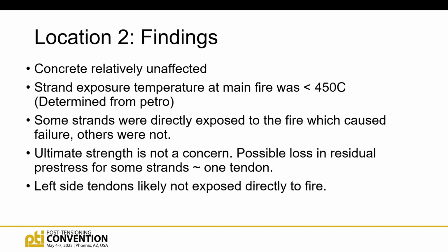So our conclusions, and it worked out pretty well for the DOT, the concrete was relatively unaffected. We weren't concerned about that pre-stressed top slab, which was the main thing that caused them to reject that other span. The strand temperature during the fire, at the main fire, the biggest fire, was less than 450 Celsius, determined from our petrographers, so that's good news. That tells us that the other strands, which are at lower temperatures, were likely less affected or almost unaffected by the heat.